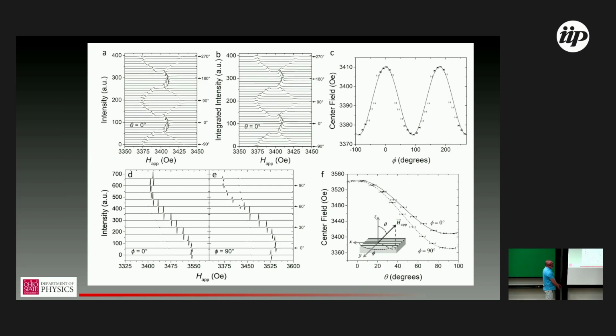Okay, and then here's a bunch of stuff going on, sort of similar to the characterization that I showed for the E-beam patterning, and just sort of stepping through how we can get quantitative understanding of what's happening here. So the top left panel is just the differential FMR scans as they come out of the system. To the right, it's integrated to make the peaks more evident. And you can see at the bottom of the scan, there are 2 peaks visible in the system, and they come together and they look like they're going to cross, but then you have this gap, and they just never cross, and then they keep going.